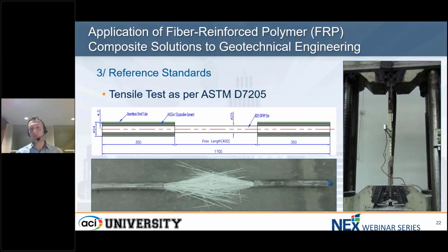But maybe for some of you who might not be so familiar, the specificity of FRP bars is that we always need to test them in full section of bars. We cannot characterize a coupon sample of the material because the properties are not linear with the section. There's a phenomenon called shear lag, which means the properties will not remain the same as the diameter increases. And also the sample needs to be prepared specially to not damage it in the clamps of the tensile machine, the UTM. That's why you see this potting sample, as we call them: a steel sleeve with a non-shrink grout to ensure the GFRP bars are well protected.